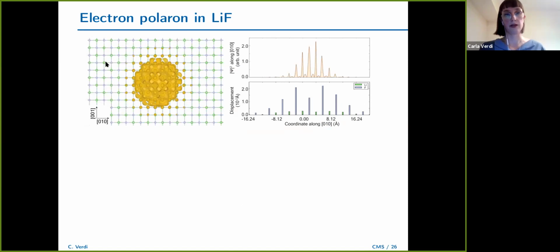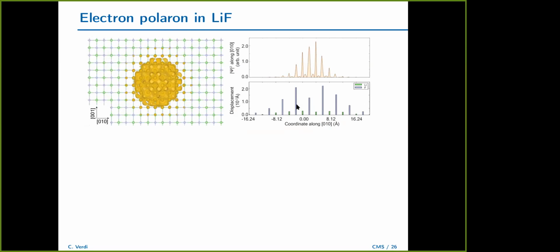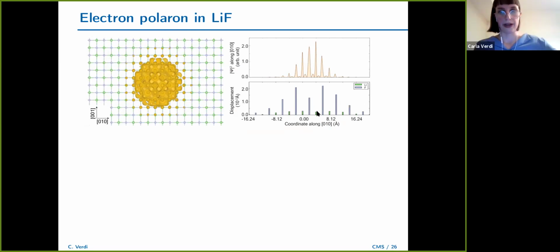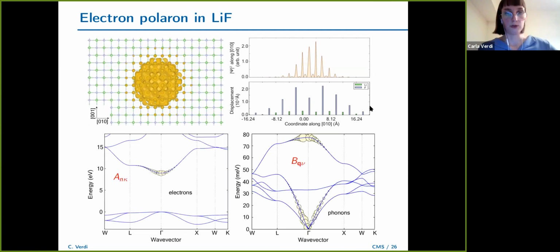By solving our polaron equations, we can actually have a realistic view of the electron wave function. We can say what is the shape. This is mainly like an S state. The radius is about 10 angstrom. Here in this plot, you can see the atomic displacements. In green, the lithium, and in blue, the fluorine atoms. So you see how the atoms displace over what range. And you see that, for example, the fluorine atoms are the ones that displace the most due to the presence of this added electron. We can actually do more with our theory.